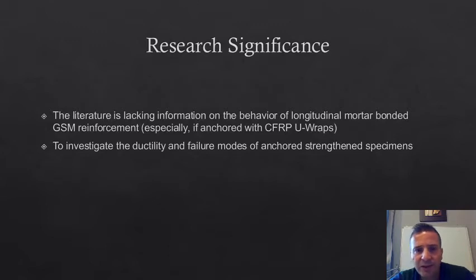And the research significance, as I told you, is that the literature is lacking information on the behavior of longitudinal mortar bonded GSM laminates, especially if anchored with CFRP U-wraps. We need to investigate and compare the failure mode, strength and ductility of the anchored specimens with the non-anchored ones, and also with a control and strengthened beam specimen. So in total we have 4 beams: 1 control, 1 strengthened with 2 sheet layers bonded with mortar but without anchors. The third one is the same as the second one but with end anchors, and the fourth one is with intermediate anchors.